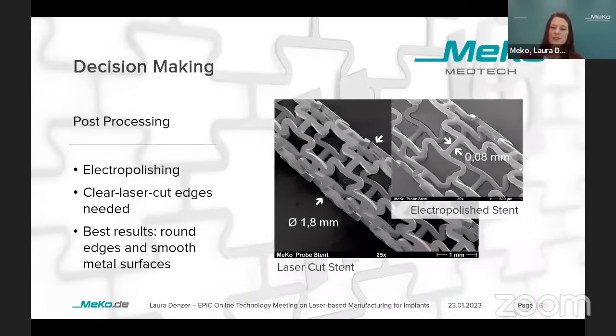And then for our post processes, we do electropolishing, for example, because for a lot of implants you need a really round edge and no sharp edges, which could harm the body from the inside. And for this, we really need those clear laser cut edges I just showed you beforehand. As you can see on the bigger picture, it's before electropolishing, it's just the laser cut stent. And on the right-hand side, you can see the electropolished stent with the really good round edges and in the end, smooth metal surfaces. Even though the struts of the stents are really, really small, we still achieve really good results.